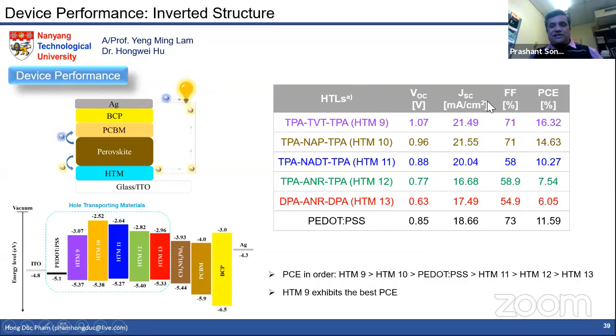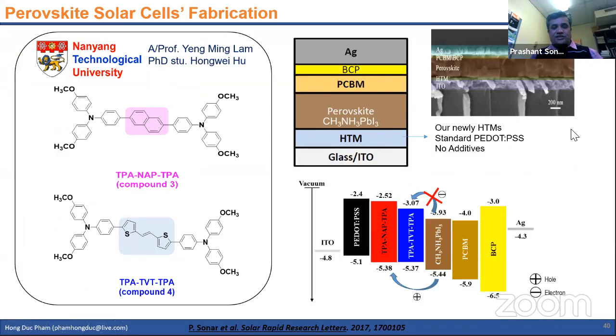Looking at all these HTLs, the power conversion efficiency values are given here. We compare that also with PEDOT:PSS in one of the cases. I will show you shortly. But we got 16.32% as the highest efficiency. Again, this work, when we did it, was the very start. When my PhD student started, this was a warm-up activity, to get a new molecule and see what kind of performance we get. So in this case, we use the additive with perovskite and our HTM.